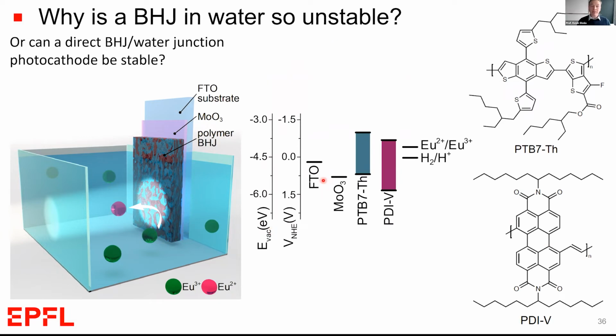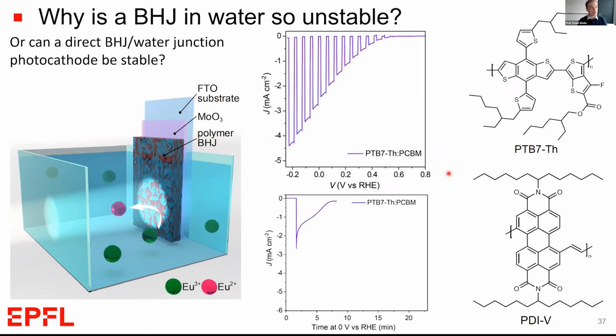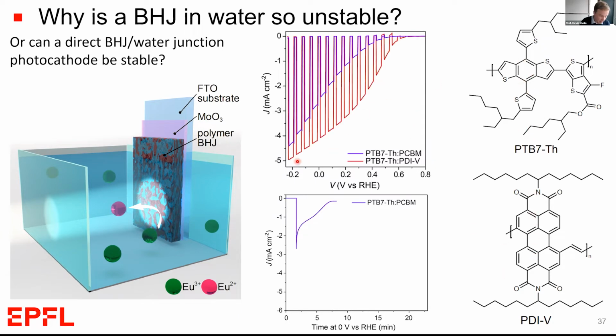However, we noted from some recent work in the photovoltaic field that these fullerene-based acceptors aren't so stable, and they cause a problem even in the photovoltaic application. So we thought maybe replacing that with a non-fullerene-based acceptor like this PDI-V could change the performance. And when we made a new photocathode with these materials, wow, we got a little bit better performance as a photocathode, but more importantly, we see a huge change in the stability.